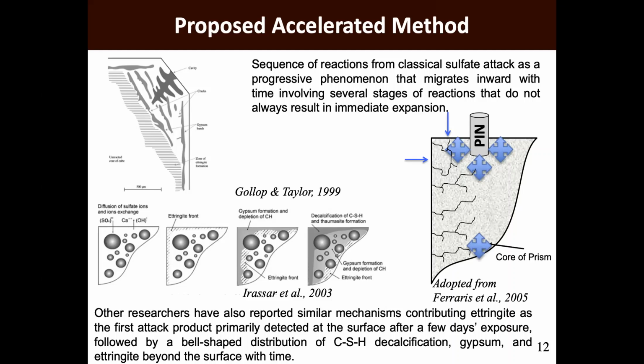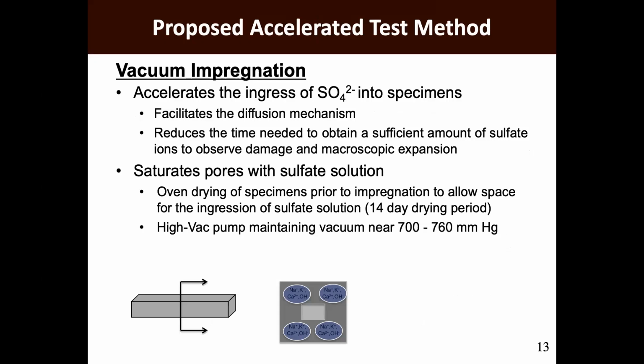And so what we end up having is a proposed method based on a vacuum impregnation system. Essentially what we've done is vacuum impregnate our samples with sodium sulfate in this particular case. We dry out the sample in an oven for a period of time, and then we put it into a vacuum system and introduce sulfate and allow that to be sucked into the sample, so that you eliminate the diffusion coefficient. So you allow the sample to be completely submerged in sodium sulfate, so that you accelerate the attack that would happen, particularly because, at the end of the day, what we're trying to do is just initiate the chemical reactivity and see how much chemical reactivity could occur with a particular cementitious system, right?